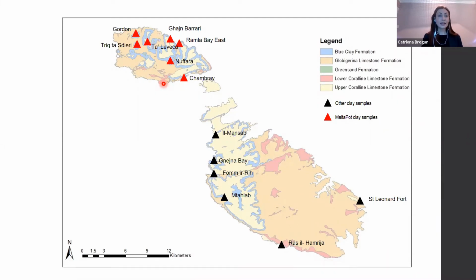And so to this end, the project went out and sampled 7 sites, all in Gozo. And then to this, we also added 6 sites from Malta, which were sampled by a previous study that had been based at the university. So in total, this gives us quite a good picture of the different clay outcrops that are present across the 2 islands.